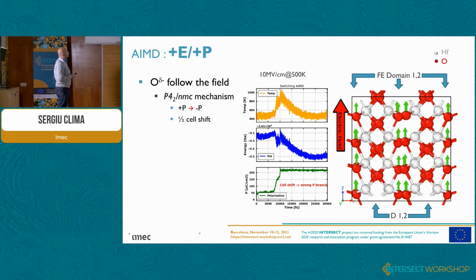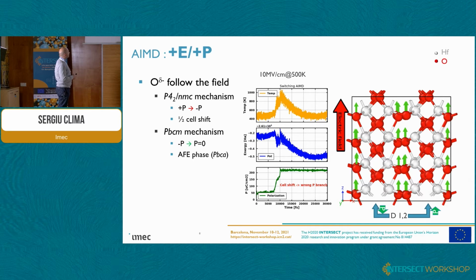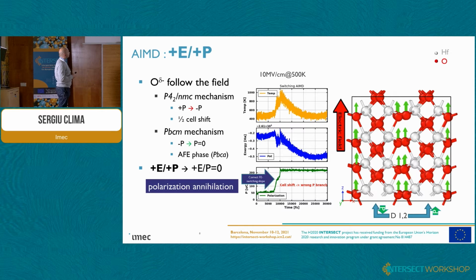And all these changes in the material lead to the absolutely correct behavior of the total polarization change. So it's quite difficult to understand by looking at the system, because in the end we end up with a completely centrosymmetric system, no polarization. But from the ferroelectric change point of view, this slope is the expected slope, and this is a valid ferroelectric switching going over a smaller barrier.